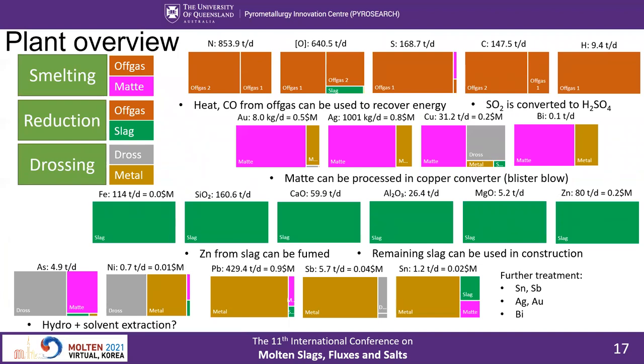This slide shows the overview of three stages. Main outputs are off-gas streams from the smelting and reduction stages — the first is typically processed to make sulfuric acid, and the second may contain carbon monoxide as a source of energy. Other products are liquid matte produced at the smelting stage, slag from the reduction stage, dross, and lead metal. The diagrams represent partitioning of elements among these streams. Copper, silver, and gold are concentrated in matte and can be transferred to copper converters. Zinc in the slag can be recovered by fuming. The remaining clean slag can be suitable for construction purposes, and research on leachability of slags is required to ensure safety.